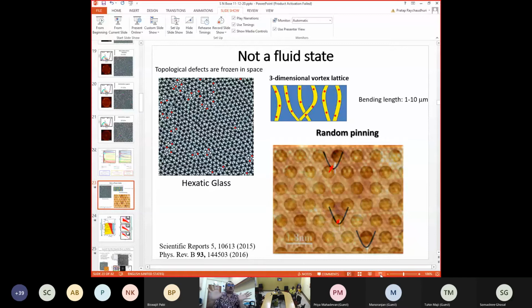We saw that there is no change at all. Each image is effectively superposing with each other, except for the noise level, which sometimes shows a very slight change here and there. And if you particularly see topological defect, they are not moving anywhere. So they are remaining wherever they are. So which means that I don't have a fluid state really. What I have is a glass. It's like my window glass, which is completely disordered like a liquid, but it has no temporal activity.